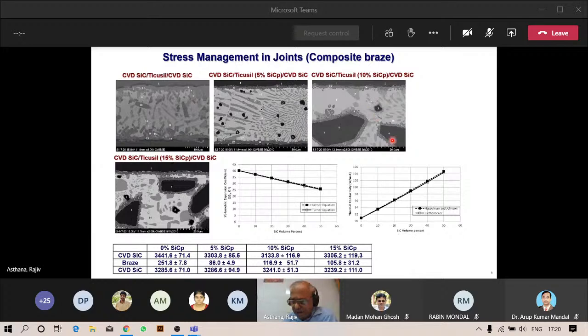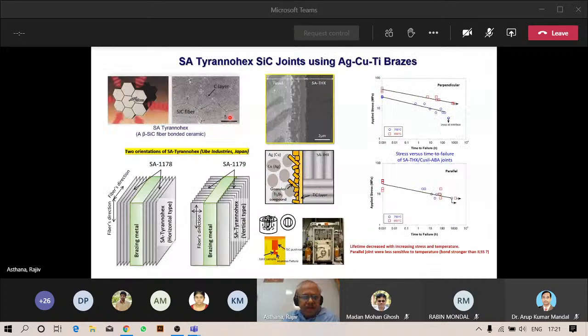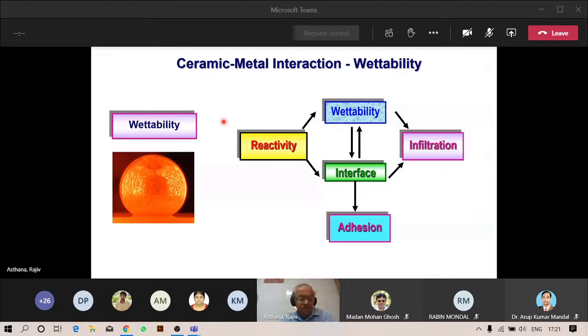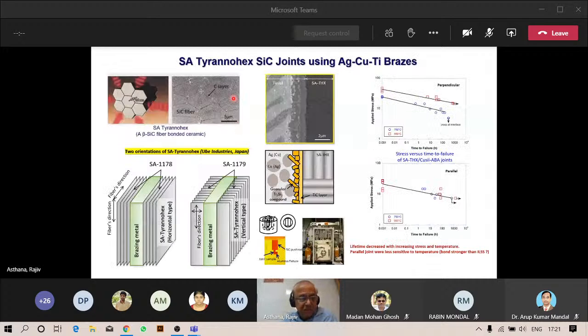Other things that people have tried is to use a porous interlayer instead of a composite braze or multi-layer. You can use a porous layer in other applications here. Let's see. One of the composites that we looked at was basically a silicon carbide material. It's called SA Tyrannohex, contains silicon carbide fibers, beta phase, and this is a product of Ube Industries from Japan. And so the fibers, they look like this here.